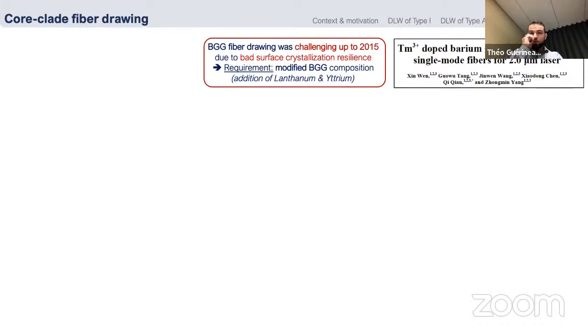My last 3 slides will be on the fiber drawing of the BGG composition. As you may know, it's still challenging, but no one was able to fiber draw BGG composition up to 2015 due to bad surface crystallization resilience. And what has been succeeded by Wen et al. is that by modifying the glass composition through the addition of lanthanum material, they succeeded to fiber draw BGG.